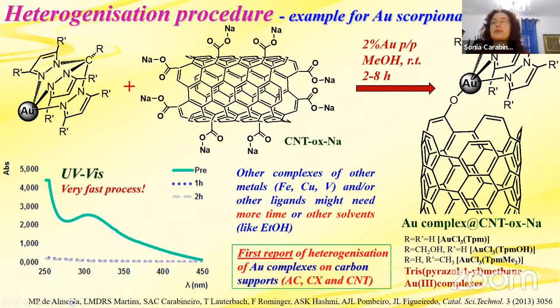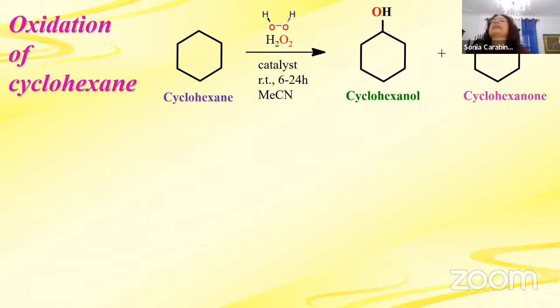And this was the first report of heterogenization of gold complexes on carbon supports. Before, there was only heterogenization on oxides and other materials, but on carbon supports, this work of ours was the first one. And those catalysts were tested for the oxidation of cyclohexane, to give cyclohexanol and cyclohexanone, so the alcohol and the ketone.